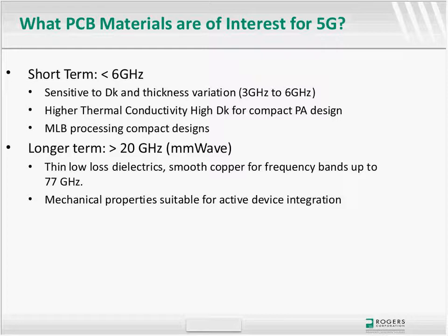We really start by looking at two broader frequency bands. Sub-6 gigahertz is what we're seeing in the early phase of 5G, which sometimes gets blurred with LTE Advanced or LTE Plus, before going to full IMT-2020. In these frequency bands, the sensitivity to variation is such that it's important to control thickness variation to have very repeatable circuits. High thermal conductivity and maybe even higher dielectric constant values to reduce the size of the circuit boards are also something we're seeing. And of course the materials being used must be processable in a way that allows multi-layer board designs.